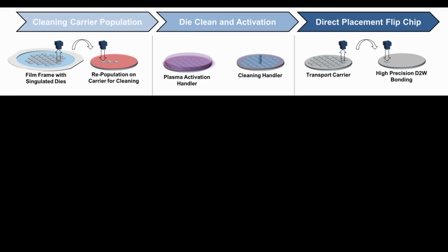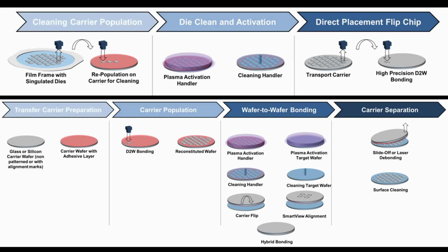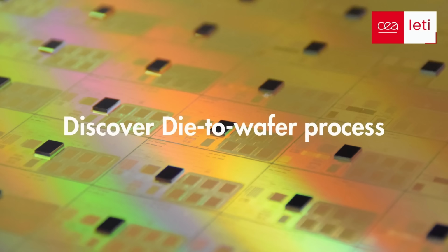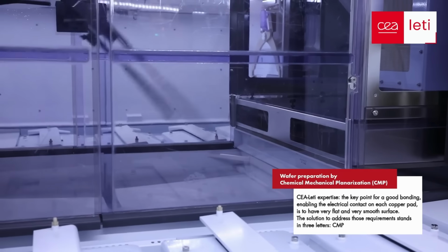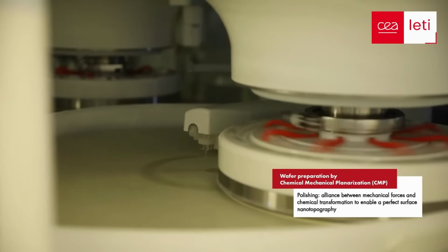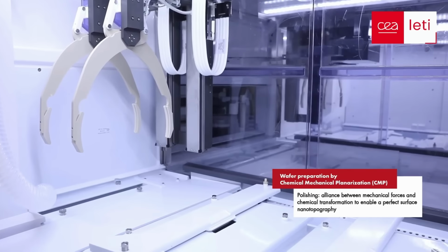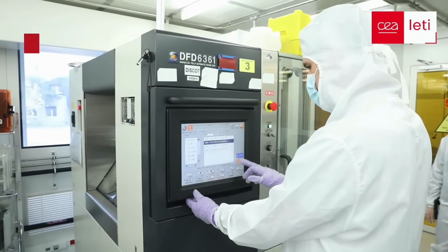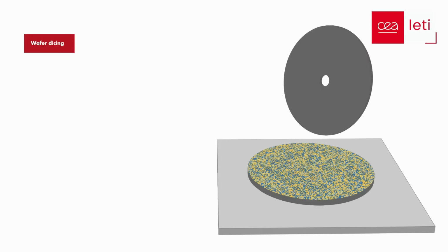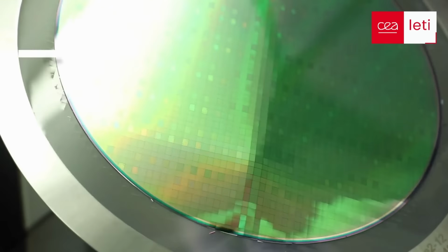Chip-to-wafer has two different ways of aligning the chips once they are cut and sorted. You can either place the top chiplet directly onto the bottom chiplet, or you use so-called reconstituted wafers. This means you are basically rebuilding or reconstituting the initial wafer, but this time only with working chips. So you take the original wafer, dice it, test the chips, and then you place the good ones back on a new wafer. You can do this with only one of the chips. So for example, you could bin the cache chiplets, place them on a carrier wafer, and then hybrid bond them to unbinned CPU chiplets, or the other way around. Or you can bin both chiplets and use two reconstituted carrier wafers for the hybrid bonding process. The bonding process itself then looks exactly the same as wafer-to-wafer bonding.